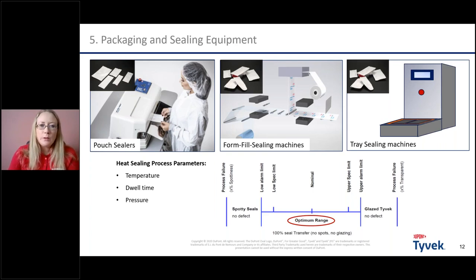And now it's very important to define the optimal range of those parameters. So not to only seal and validate nominal parameters, now it's important to define like minimum temperature, dwell time, pressure, where you have a good and complete quality seal, and then not going so high that the seal already starts to get burned or transparent, so still good quality seal. So this will be your range, and then usually for commercial production, of course, you will be sealing on nominal conditions.